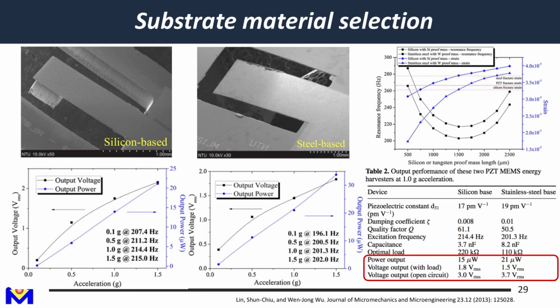Well, when we did this kind of optimization, we found that this stainless steel substrate material has another very important characteristic. The stainless steel substrate is a metal material. Metal material, from a material perspective, is a ductile material. Ductile material means it has a yielding or necking phenomenon. And silicon or PZT ceramic is a brittle material. Brittle material is like glass. When you drop it onto the ground, it breaks. It cracks. And for metal material, it's ductile. So if you have a metal cup that falls onto the ground, you only see a dent. It won't break, right?